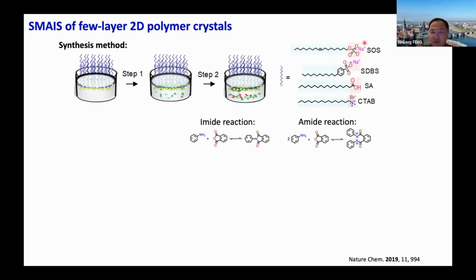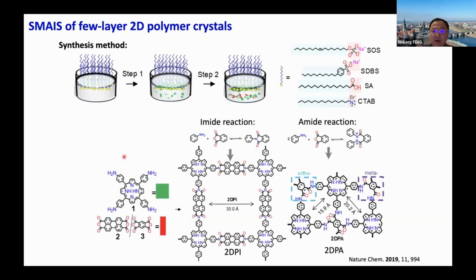So we use the negatively charged surfactant on the water surface, and they can guide the porphyrin molecule on the water surface with the pre-organization. And we add the second monomer, either anhydride monomer, so they can polymerize with the porphyrin molecule to make the imide bond or amide bond. And this ends up with very crystalline materials with very thin layers.